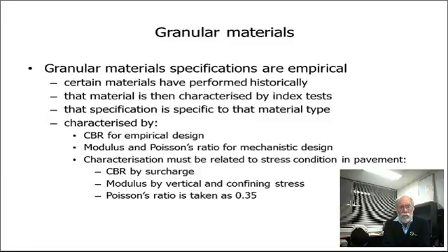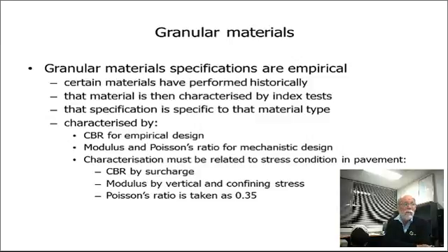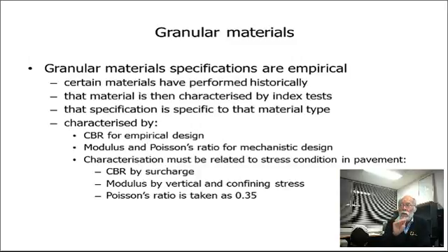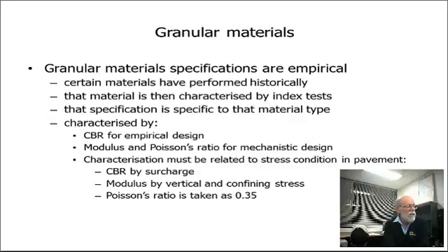The CBR value — you need to know the conditions under which that CBR test was done. For a base course, the surcharge is very low, so 4.5 kg is probably applicable because all you'll have over the top is asphalt. These materials are stress dependent. At the top of the granular layer — the thinner the asphalt — the higher the modulus that material will develop. As the asphalt thickens, you need to apply a lesser modulus value to that same material because it's not under the same stress. The Poisson's ratio stays the same but the modulus value will vary. The modulus is defined by vertical and confining stress.